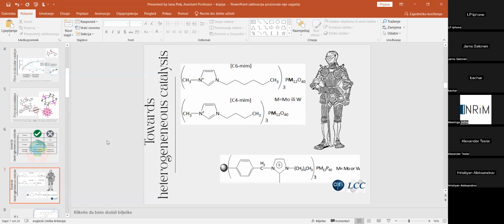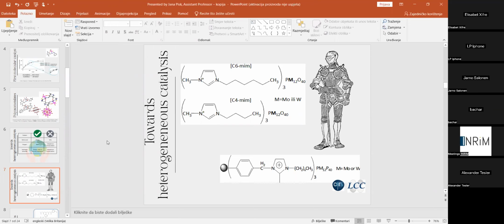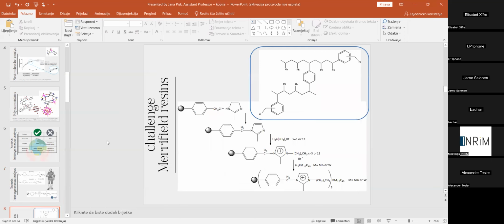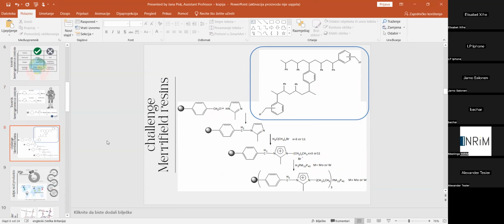We moved to the area of heterogeneous catalysis, and it was the main point of my postdoctoral research. We started to prepare simple molecular catalysts that are shown on the upper part of this slide. They were prepared by a very simple reaction using commercially available polyoxometalate acids, and we made complexes with something called an ionic liquid. The idea was to fix those catalysts on some kind of support. For this support, we decided to use Merrifield resin, which is used for the synthesis of peptides, and we gave it another role as a support for our catalysts.